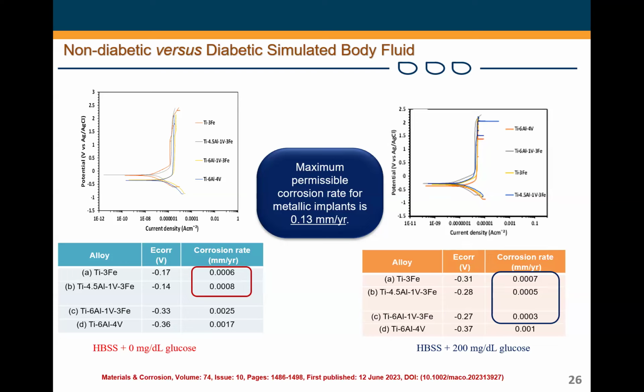And what we found is that in all the iron-containing alloys, the thickness of the titanium dioxide is actually higher than that of Ti64, which has 4% vanadium. And this seemed counterintuitive, because we expect that maybe iron should accelerate the corrosion behavior of titanium alloys, but this is not what is happening.